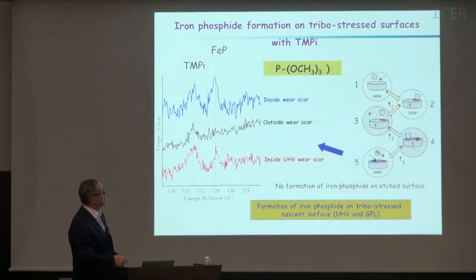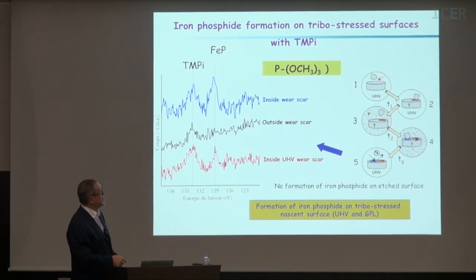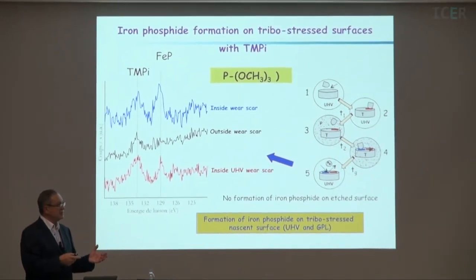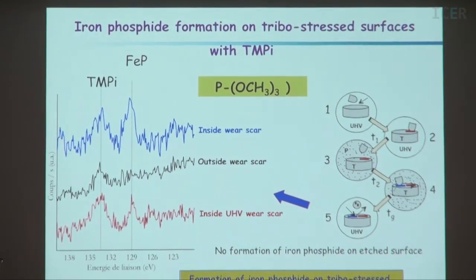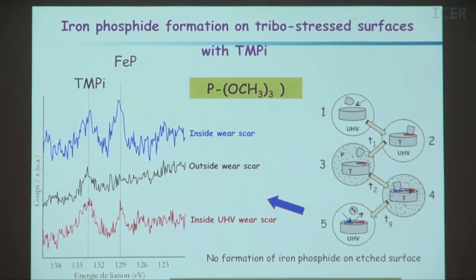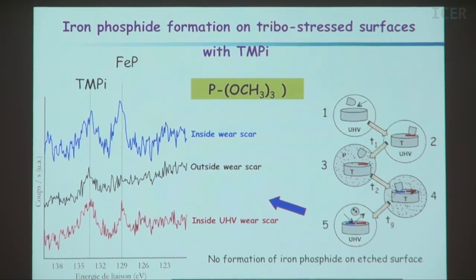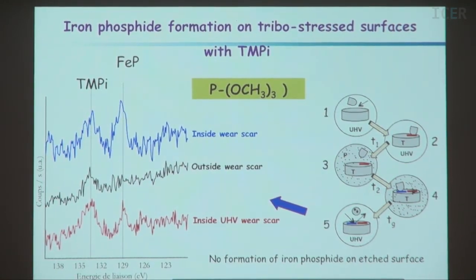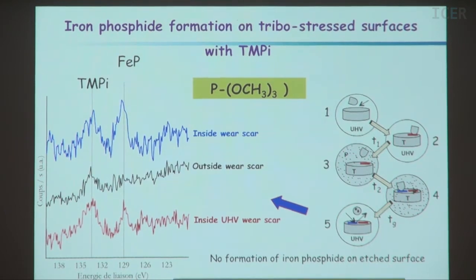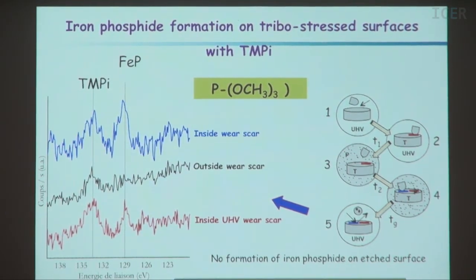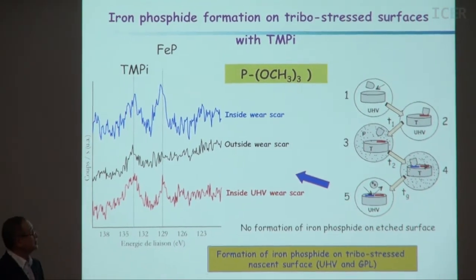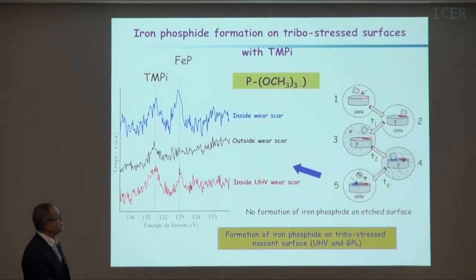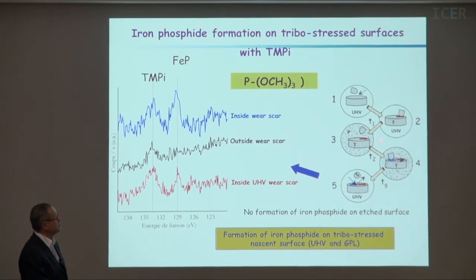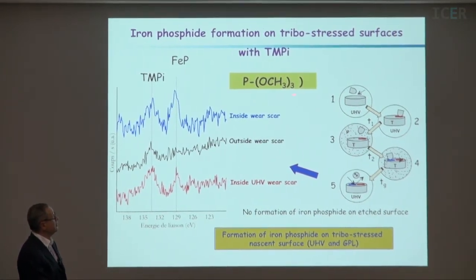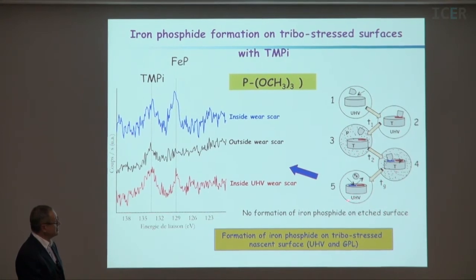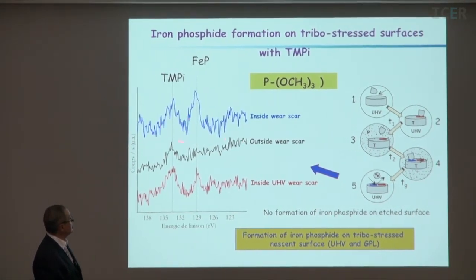So again, we made it in vacuum, we removed the oxide, because in the case of gears, the contact between gears is very severe. And very often the oxide is removed by the gears because the contact pressure is very high, maybe 2 gigapascal. So the oxide is removed during the gears and exposed to the lubricant. So we remove the oxide here. We make a friction in vacuum, expose to the gas, trimethyl phosphite here, and again, we go to the analysis. And this is the result.